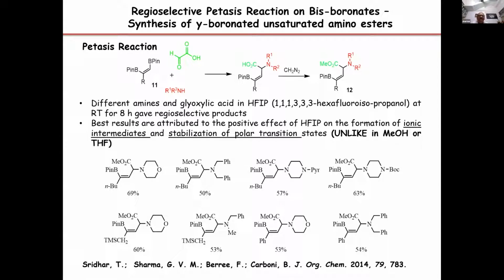I have shown here a variety of different amines that were utilized for the condensation in the Petasis reaction, as well as different side chains. Alkynes were used for the preparation of bisboronates to get the condensation products in 50 to 60% yields. And interestingly, the Petasis reaction has occurred at the terminal Bpin bond, leaving the internal Bpin untouched, even after a longer duration of time.